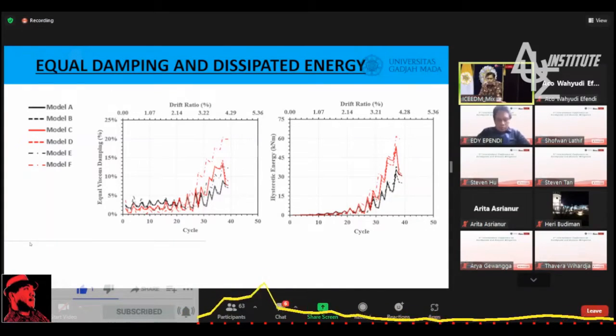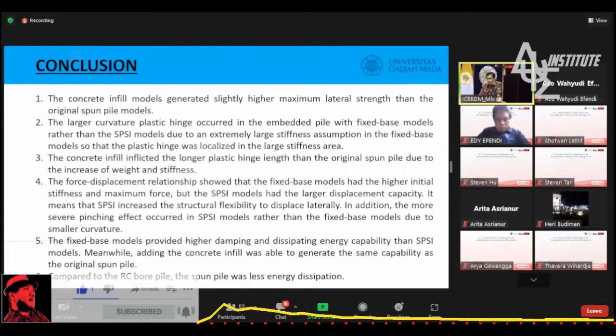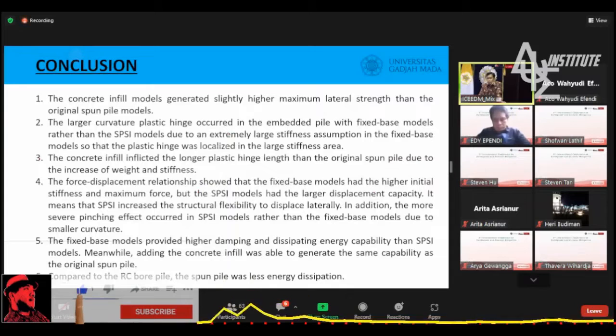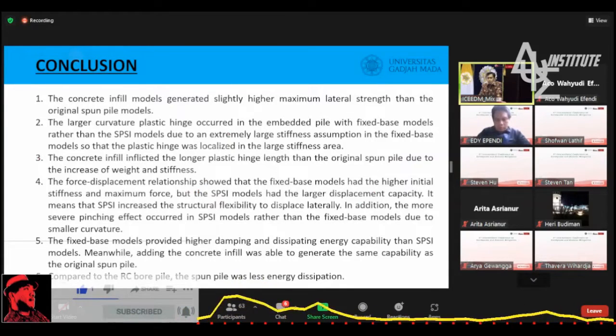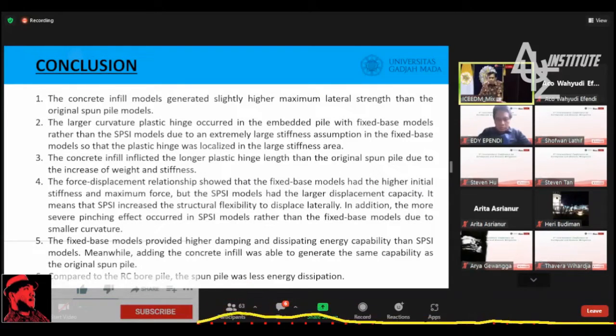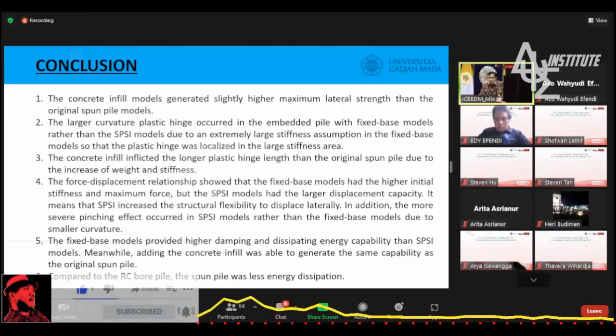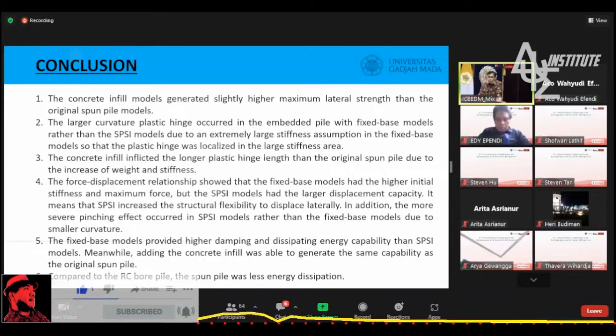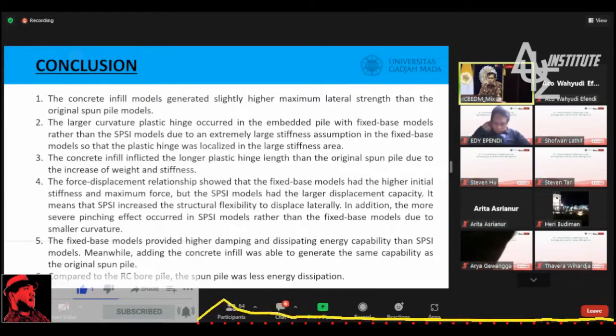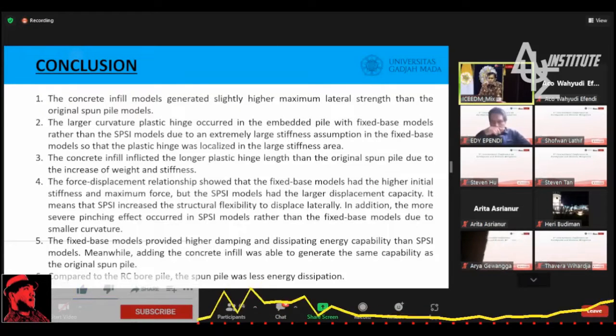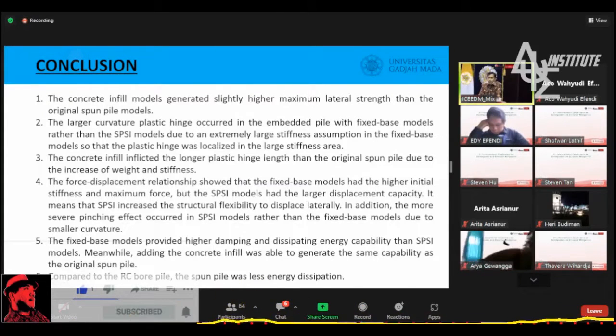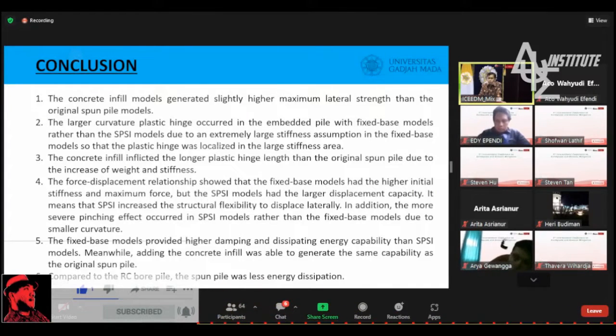So we can make some conclusions with this study. Using the concrete infill, it can achieve a slightly higher maximum lateral strength than the original spun pile model. And then the larger curvature plastic hinge occurred in the embedded pile with fixed model rather than the SPSI model, due to the extremely large stiffness assumption in the fixed-base models rather than the SPSI models